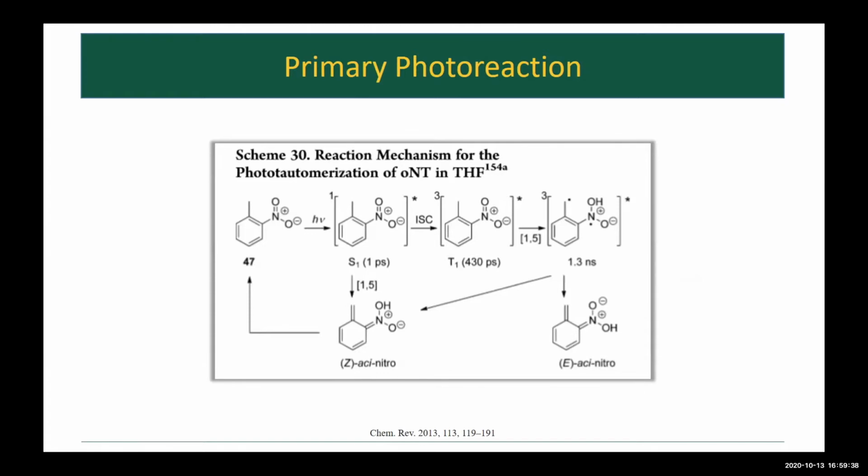This may not be the best time, but I think it's fair that I explain the mechanism of possible cleavage. Generally, in papers that I've read so far, they say the primary reaction is usually due to an excitation of this nitro group. It gets excited through the intervention of UV radiation and is able to abstract a hydrogen from the neighboring carbon, and it creates what I believe they called a biradical unit. It was able to go into different nitro forms such as Z and E, and this is the primary mechanism of any sort of cleavage to occur regarding this and whatever it is attached to.